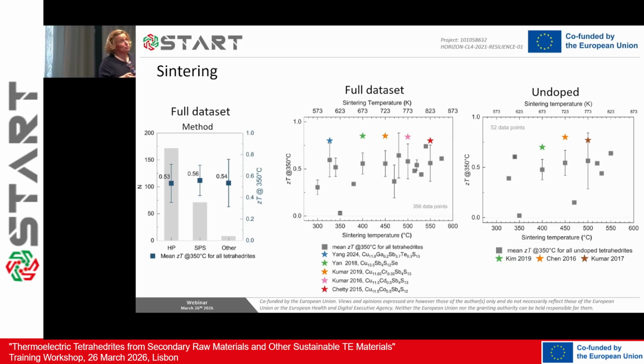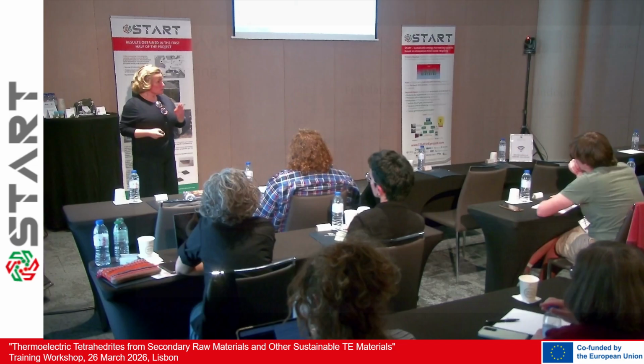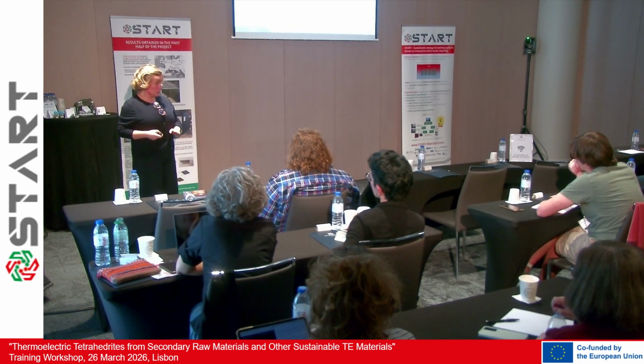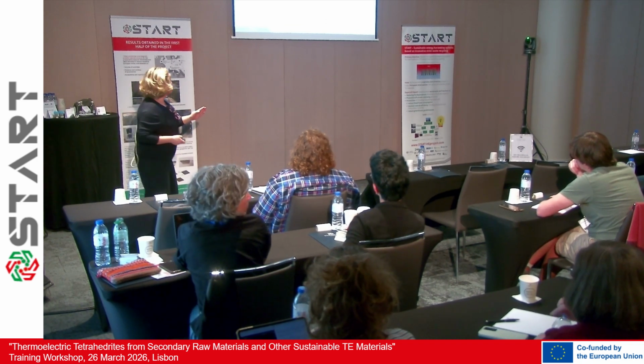So we try to plot the full data set again. To make sure we were normalizing with regards to the temperature dependence, we chose to plot everything at the ZTs at 350 degrees. This was also because 350 degrees was the temperature we decided at the start was the surface temperature for our devices. So, okay, let's plot at 350.